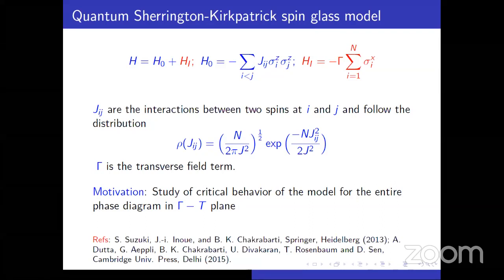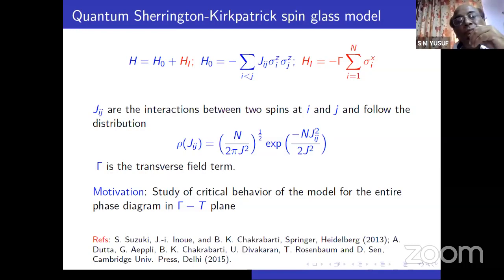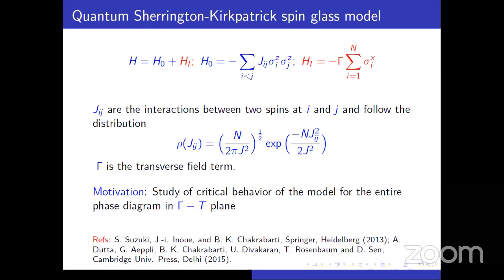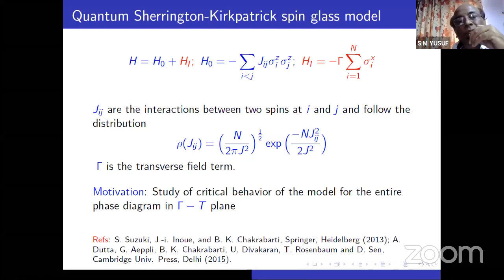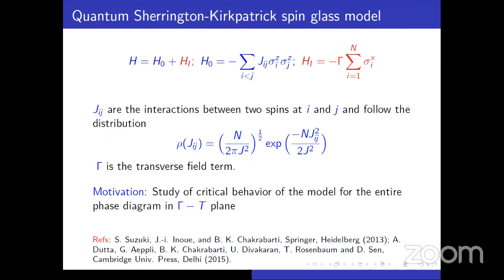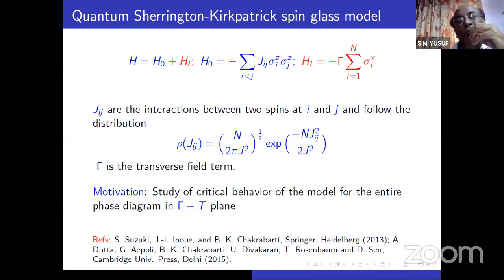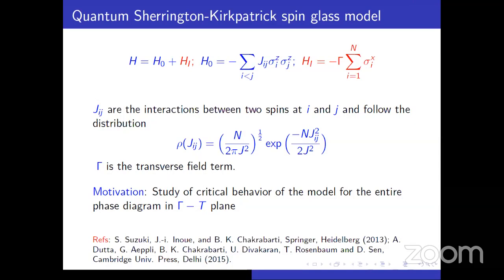But then you have plus Hi, which contains sigma i x. Sigma i x doesn't commute with sigma z, so this is a non-commuting field. This sigma i x actually changes the eigenstates of sigma z, from 1, 0 to 0, 1. So this state flips: up spin becomes down spin, and the probability of that change depends on the tunneling field. So it is this quantum term which is responsible for all these advantages. We consider the whole system in a thermal bath, so temperature is also there.